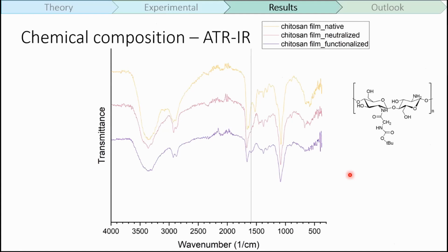With attenuated total reflectance, we then measured some IR spectra. We compared the native film with the neutralized film, and the purple line represents the functionalized film. At 1600, you can see the appearance of a new peak, which could maybe be attributed to the formation of a new amide bond in our functionalized film.